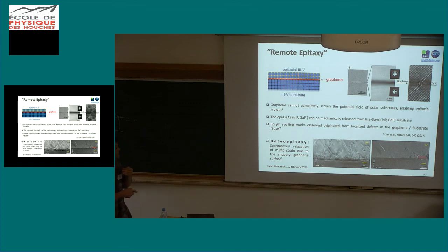And then once again, since you have graphene, the real adhesion between this epi layer and the graphene is only van der Waals, and you can peel it off mechanically. And this is kind of beautiful to me. And this year, a few days ago, they published another paper that's really nice, and you can understand it very well. Instead of using gallium arsenide on gallium arsenide, this time they use gallium arsenide and gallium phosphide. There is almost 4% difference in lattice parameters.